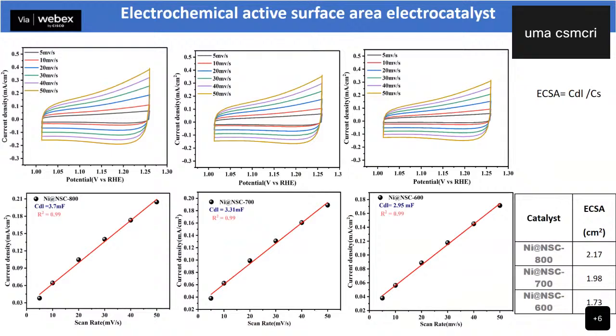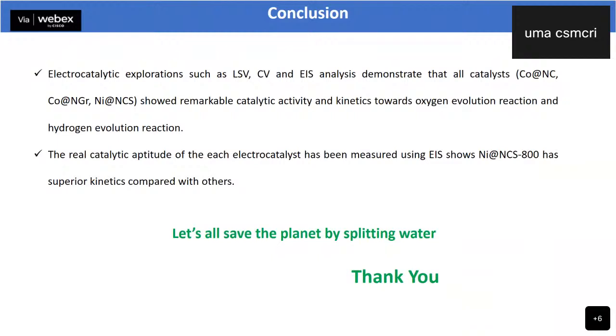Then chronoamperometry was performed to see the stability and found that the material was stable up to 48 hours without any significant loss of current density. On the basis of these results, we can conclude that all the materials have good electrocatalytic activity. However, when we talk about the potential, then cobalt-based material shows good activity with lower potential and provides more current. While we talk about the stability, then the nickel-based materials are more stable.